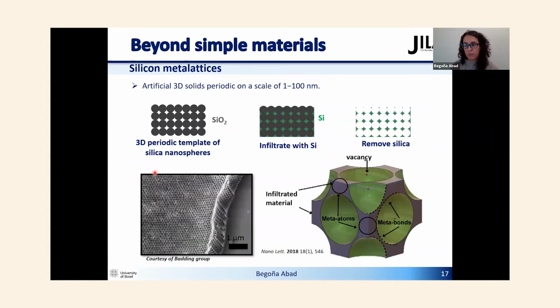So once we characterized these bulk materials, we went beyond these simple materials and started studying more advanced ones. In particular, the silicon metalattices. The silicon metalattices are artificial 3D solids, periodic on a scale of 1 nanometer to 100 nanometers. And they are made from a 3D periodic template of silica nanospheres, where our collaborators infiltrate silicon between the spheres, and sometimes they were able to etch out the silica spheres.